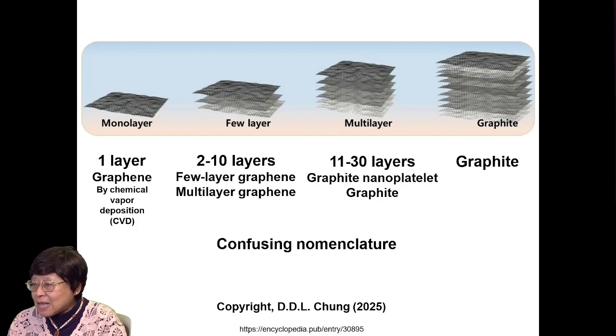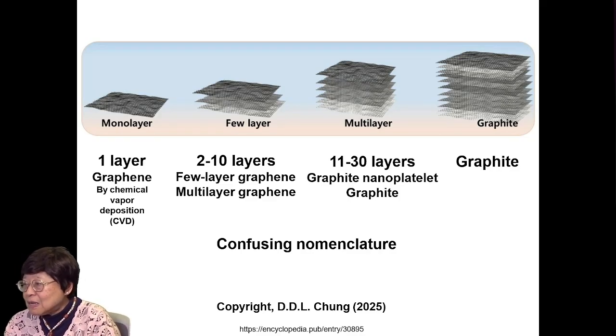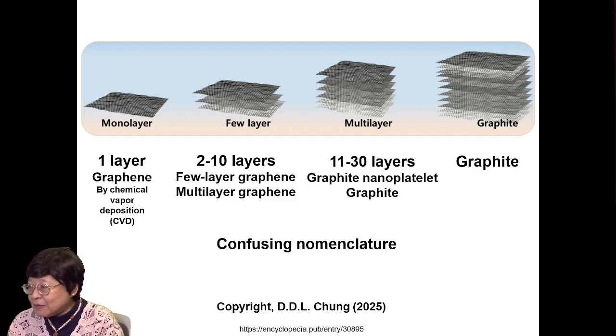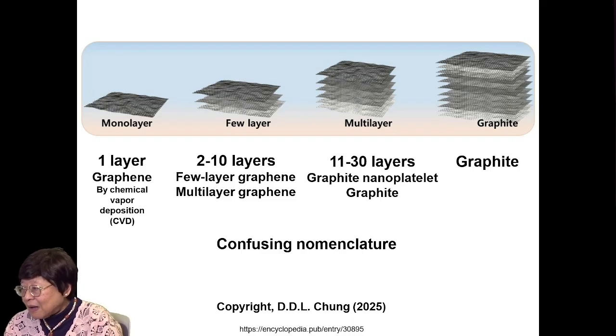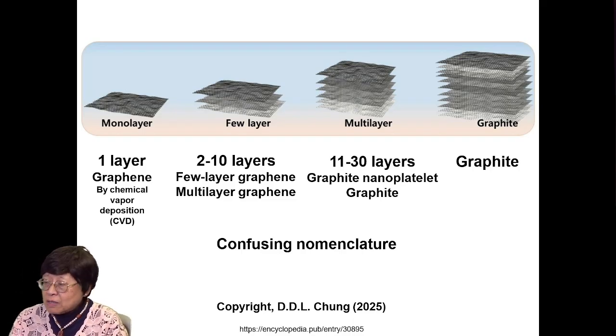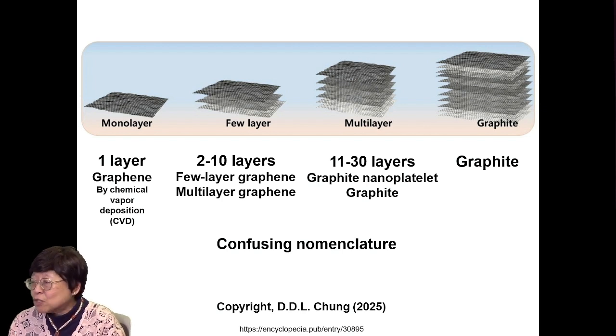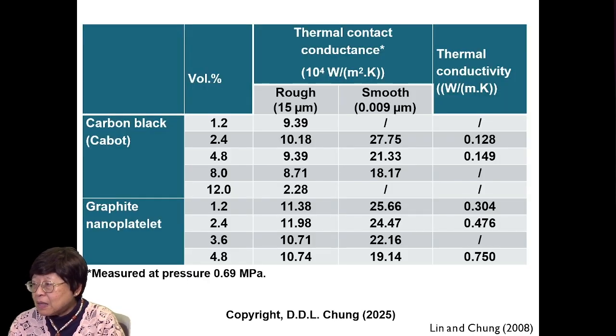The terminology is that you can have a monolayer graphene, 1 layer. You can have 2 to 10 layers, and that's called few-layer graphene. You can have 11 to 30 layers. That would be not graphene because it's more than 10 layers. That would be graphite nanoplatelet, or just call it graphite. The nomenclature is confusing because graphene is a very fashionable word, much more fashionable than graphite. So people want to call their material graphene even though it is graphite and not graphene.